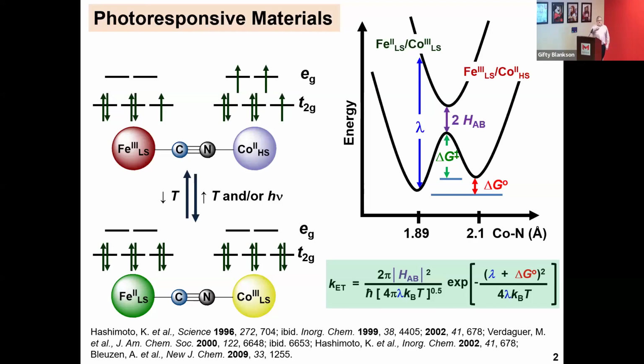These two electronic states have a difference in potential energy described by delta G standard. You have an effective energy barrier between those two states. So in other words, you can't just directly go between the two states, you have to climb a hill. Right? You have something called reorganization energy. This is blue, lambda. That's the cost of doing business, in that if you change the oxidation number of your metals, change the Lewis acidity or basicity of everything present, you get breathing of that unit. That breathing requires energy, it requires time, and if you're expanding and contracting the volume of that unit, everything around it has to accommodate that change.